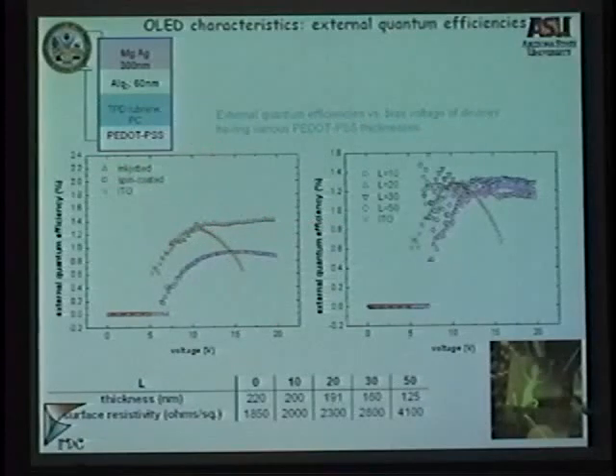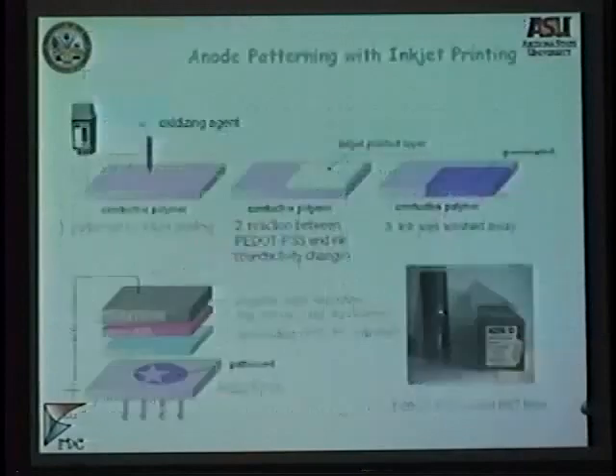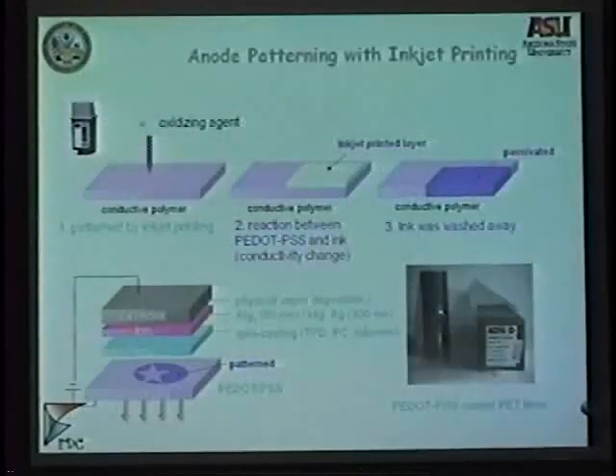You need it to maintain the quantum efficiency, especially the drive voltage as time goes by, and this is what we're testing now. And you can see here, this is the inkjet printed device. There is no ITO here, and this is just the shape we got from PowerPoint, and we printed it, then deposited the emitting layers and the transport, and you got this pretty easily achieved with no hard labor at all.